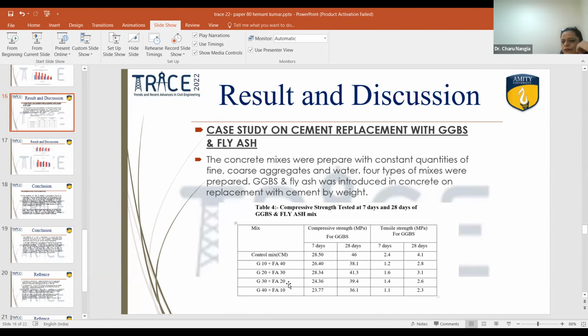So what kind of buildings will you recommend with this kind of concrete? Ma'am, we can construct high-rise buildings or bridges by using GGBS, as we get early strength and more strength, and we use fly ash in dams where mass concreting is done, because their heat production is very large, which may cause cracking. And what about the flexibility of the concrete? Will it affect the flexibility? Can we get any shape we want out of concrete, or will it affect that? No, we can get any shape when we use fly ash, as it also increases the workability.